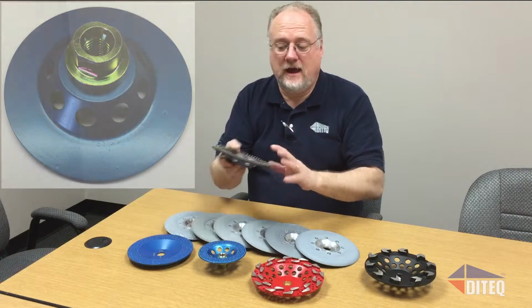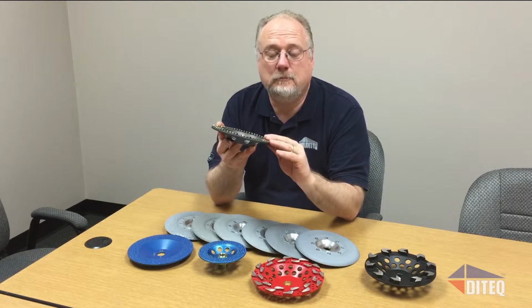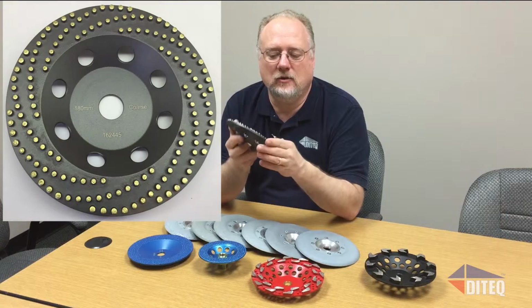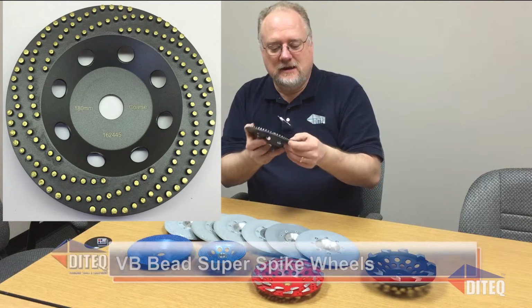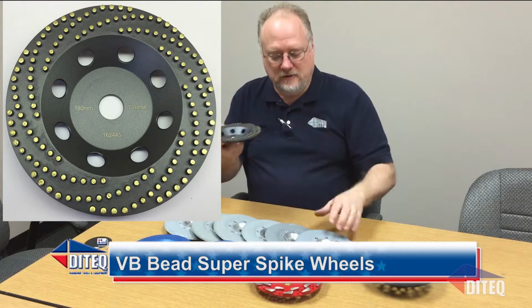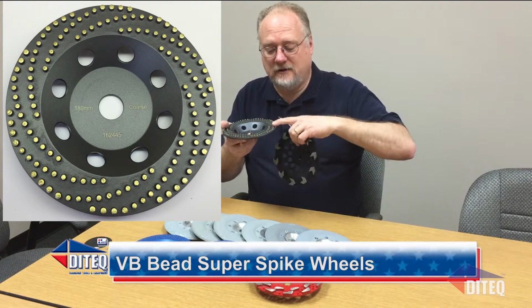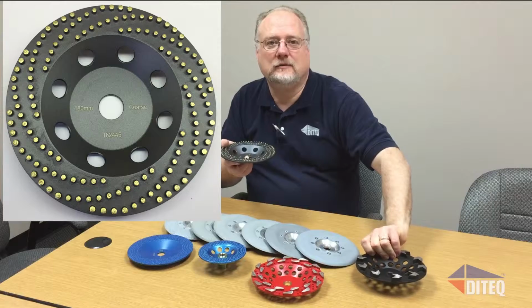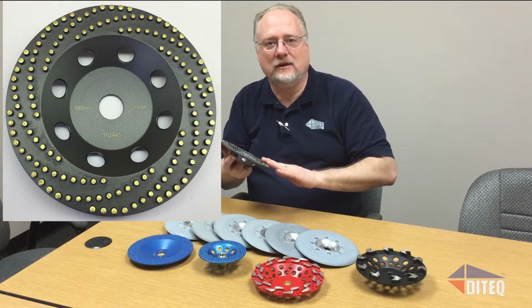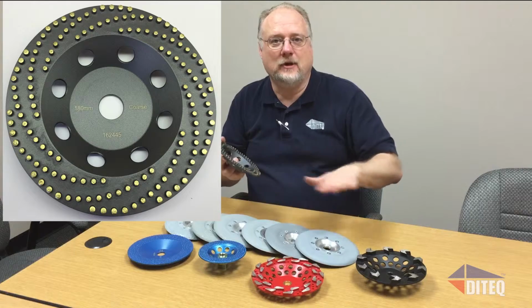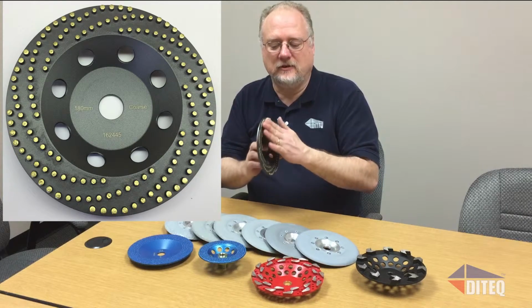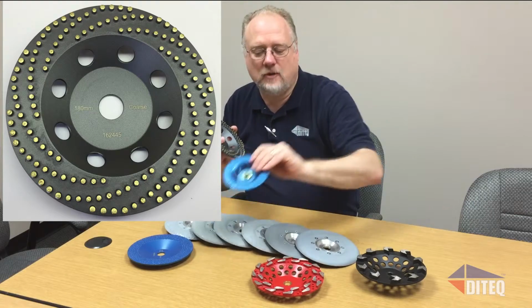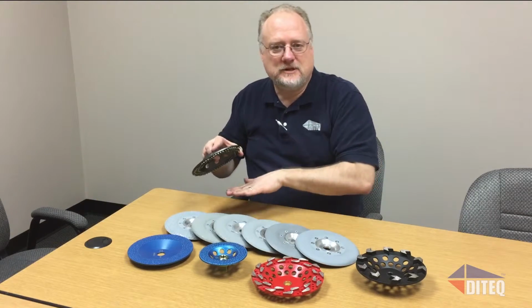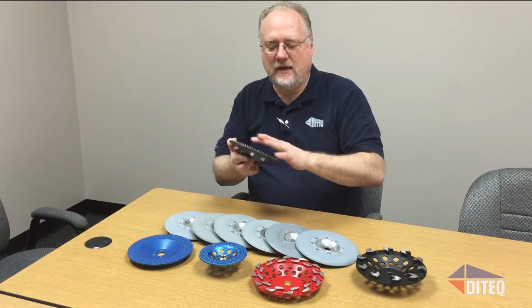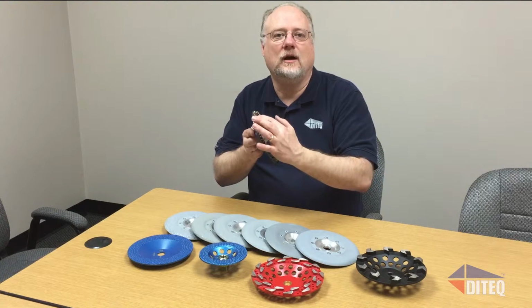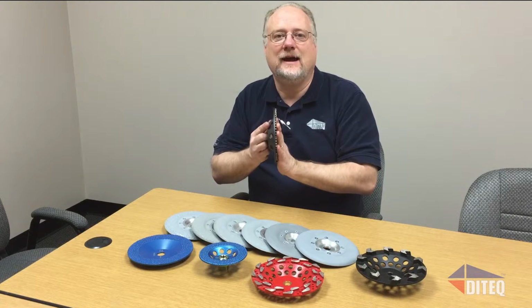But anyway, we have a vacuum brazed bead, which is brand new this year, state of the art. These are actually beads. They look like they're sintered metal product, but they're not. They're actually vacuum brazed, so the diamonds are always exposed. They're great for non-abrasive coatings, but they're also good for concrete, any abrasive coating as well. They're a bead, so they're a lot bigger surface area. They're not as sharp pointed as the spikes, so they can potentially leave a smoother surface finish, and they are largely protruded so they won't plug up with materials. So they're very quick at any kind of coating.